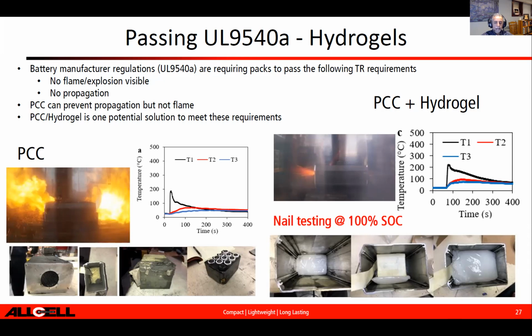And if you put hydrogel with water, sealed in this manifold, you basically direct the flame to the hydrogel. So the hydrogel, when it's ruptured, does two things. First, the latent heat of evaporation of water in it absorbs a lot of energy that allows you to quench that flame. But in addition, the vapor released will dilute the electrolyte that's coming out of the cell. And with the proper venting, you can dilute it and allow it to exit the pack without causing any flames